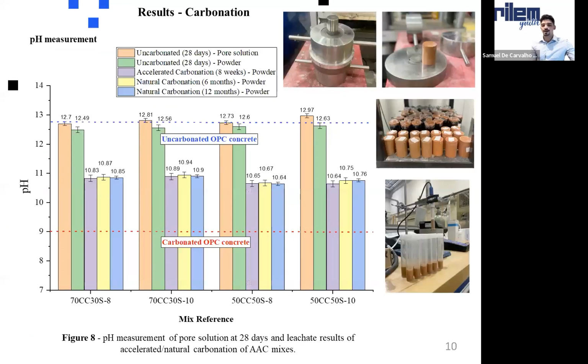So because of that, you moved to see if this area that was showing as carbonated could truly pose a risk to the reinforcement bar. So you performed some pH measurements on the same mix designs. I will just show you guys, especially the ones that were completely carbonated. And you move to the pH.